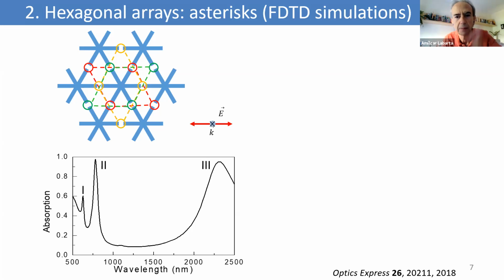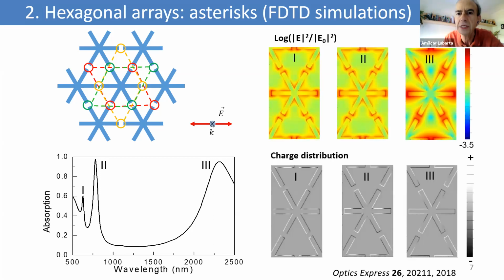We have a broad peak corresponding to near field interactions, a narrow peak corresponding to collective modes, here the electric field distribution and the charge distribution. But I am going to use this case to illustrate how the time relaxation of the system is. After the excitation of the system with a very short pulse of about 6 femtoseconds, we are going to study the shining of the system following the different modes of excitation.